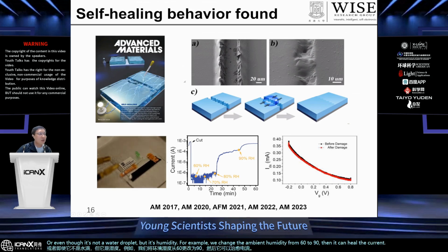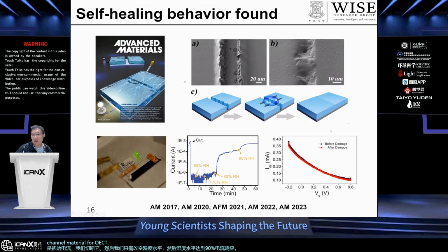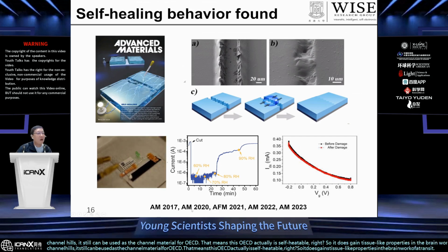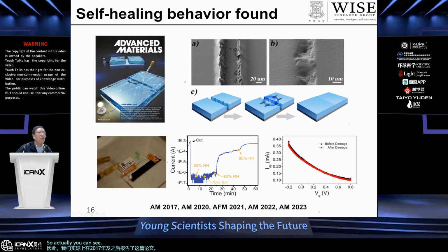This is the initial current, we cut it, and then we just change the humidity level, and when the humidity level reaches 90% the current responds, right? And after the film heals, it can still be used as the channel material for OECT. That means this OECT is self-healable, right? So it does gain tissue-like properties in the framework of a transistor. We reported this paper in 2017, and after that, you can see almost every year.